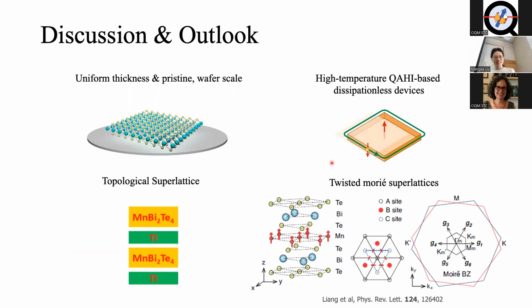Okay, so to look forward, here is a discussion outlook. Although we can achieve those pristine samples, how to grow them in a uniform thickness and at wafer scale is still quite challenging. They all seem to have some fluctuation of thickness, and from area to area they may not look the same. But the power of STM is we can look around and find local clean and neat regions. But to have a wafer scale clean sample with uniform thickness, there's still a long way to go.